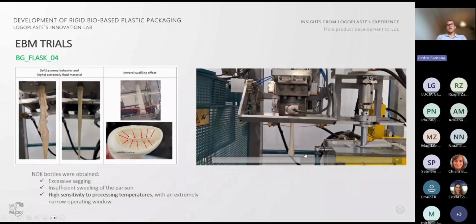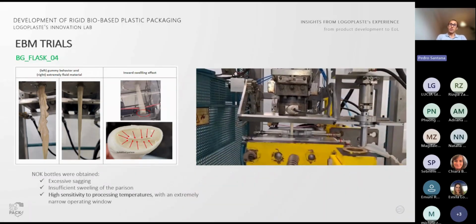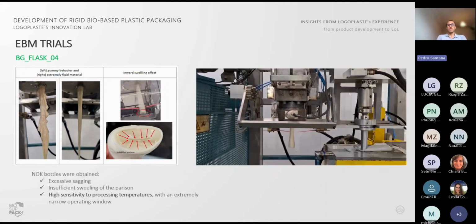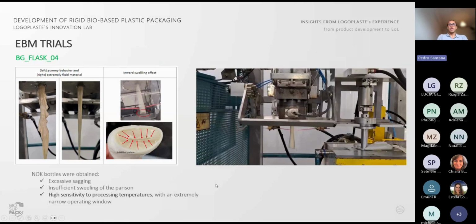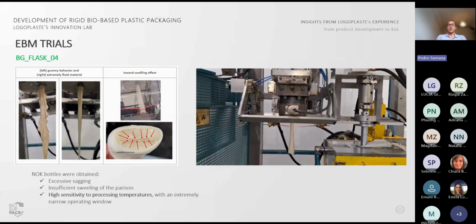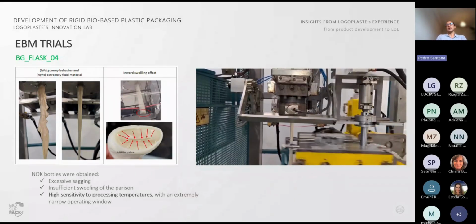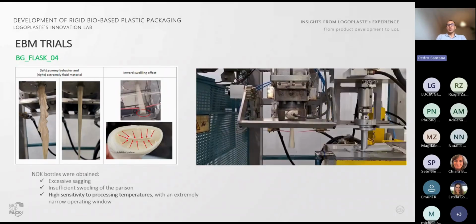Despite this improvement in materials, the material's high sensitivity to elevated temperatures remained evident. On this specific machine, there was a safety limitation preventing the use of temperatures above 160 degrees. This is a safety feature that is typical in industrial machines, which corresponds to the upper limit of the typical processing window for PHA. In addition to the thermal sensitivity, excessive sagging and lack of parison swelling were once again observed.